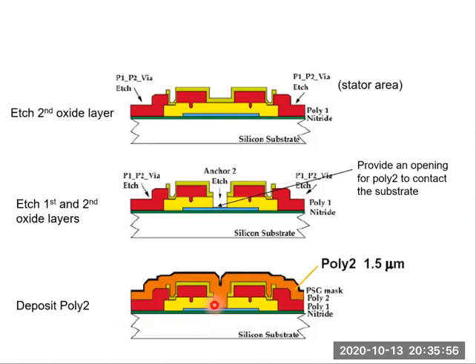The second polysilicon layer, which is 1.5 micron. Now we can see that this poly 2 layer anchors to the substrate. Right? It contacts the substrate directly due to this opening etched in this step. So it anchors to the substrate.